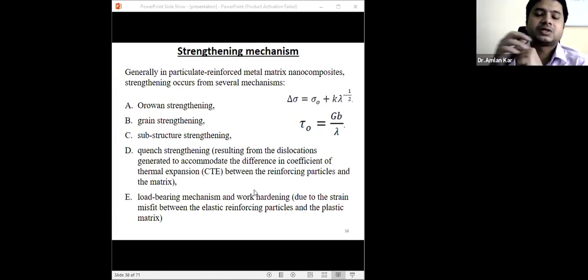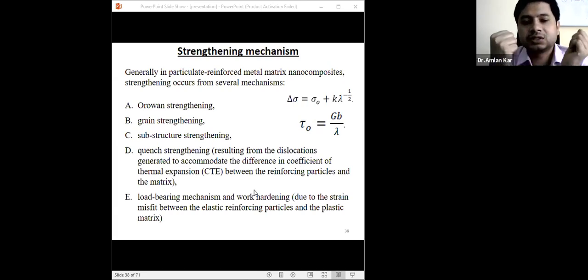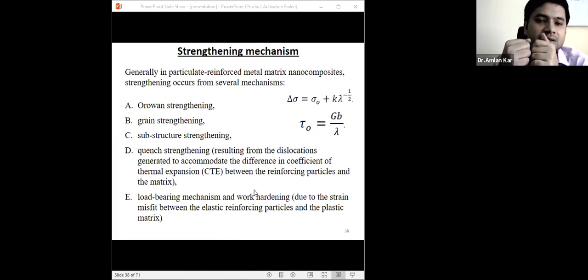thermal expansion between matrix and the particles. And load bearing capacity of the particle is generally very, very high. So during the deformation, if the particles are very, very small, the load bearing capacity of the particle is very, very high. So load is transferred from the matrix to the particle if the interface is very, very strong. And this is also due to the strain misfit between the elastic reinforcing particle and the plastic matrix.